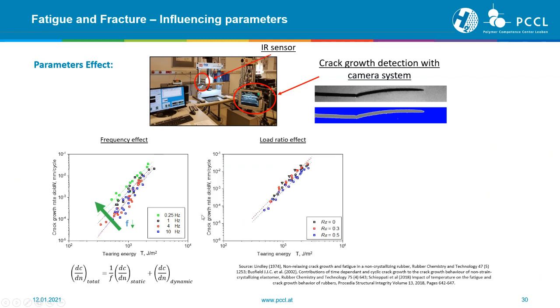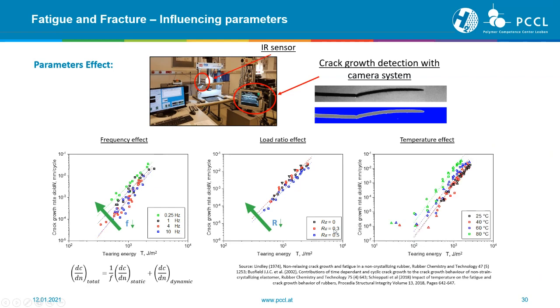We have a load ratio effect, which means minimum stress divided by maximum stress. So load ratio R of 0, 0.3, 0.5. And we've observed here a small impact with these different load ratios. And finally, ending up where we always end up, with the effect of temperature: a clear difference at 25 degrees C, 40, 60, 80. And please keep in mind that we have a log scale here, which means that from, for example, 25 or 40 degrees C to 80 are 2 decades, which means there's a big difference in this scale.